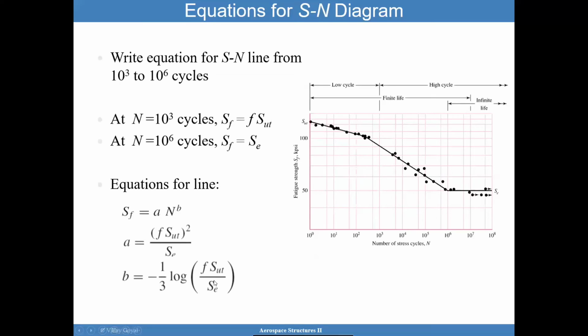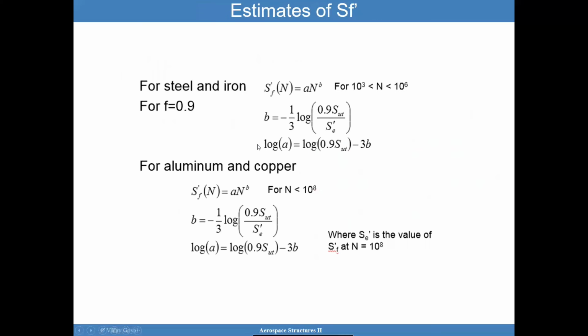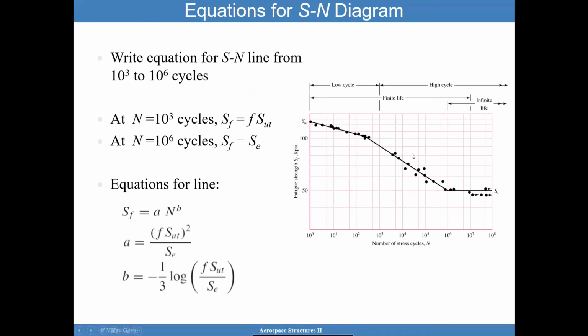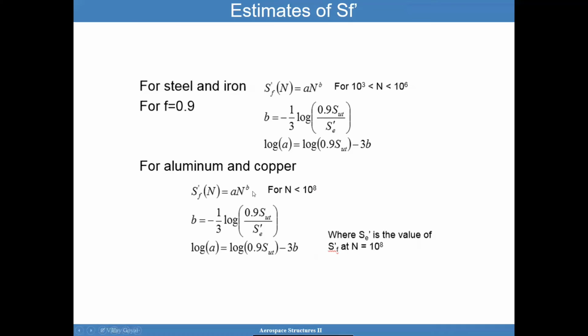As long as you can figure out what SE is, and then this f is typically taken as 0.9, but not always. It depends what the value is at 1,000 cycles. So at 1,000 cycles, it could be a fraction of ultimate strength. So for steel and iron, f is 0.9. And so then you can quickly construct these exponents, and these curves can quickly fall out. For aluminum and copper, 0.9 also.